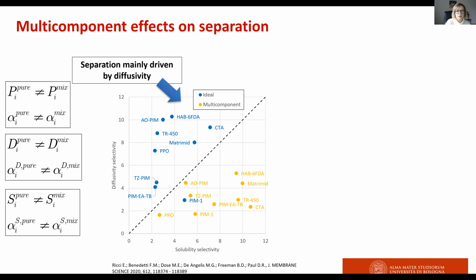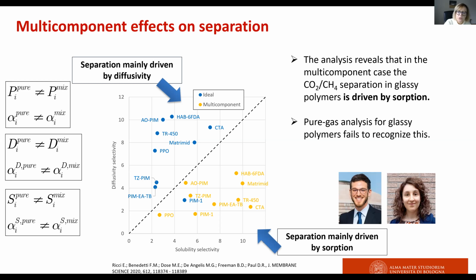In particular, this is something that was published this year. If you take a look at the main glassy polymers suitable for CO2 capture, you can see that if you consider only the pure gas data, it seems like membranes are dominated by diffusivity selectivity. While actually, if you go into detail and you take a look at the multi-component data evaluated on the same membranes, you see that the opposite is true, and the separation is mainly driven by sorption. And this again confirms the fact that solubility has a strong effect on the separation performance.